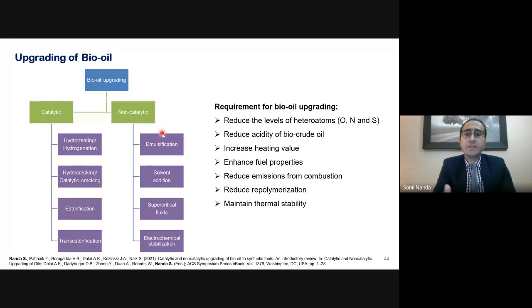Therefore, when we upgrade it, we reduce the acidity and kind of neutralize it, or bring it to a slightly higher pH, so that it becomes stable and maintains its stability for a longer duration of time without causing any corrosion to the reactors or the pyrolyzer. Now, one interesting factor to note is that when we remove the oxygen level or moisture level, then we tend to directly increase the heating value of a material. So the heating value of the bio oil is further increased.